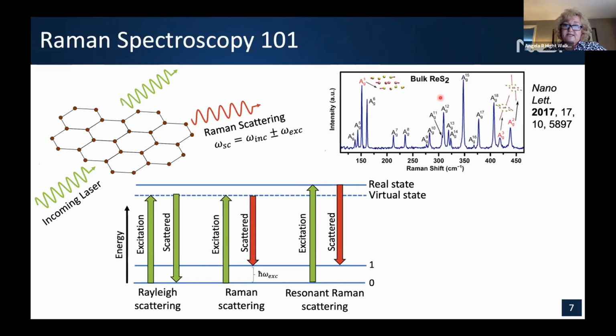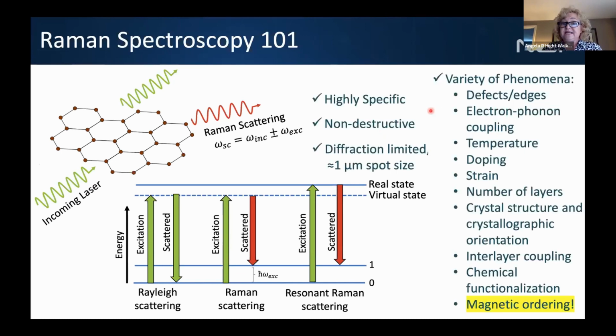So just to give you an example of how a typical Raman spectra might look, we have Raman shift along X and then intensity along Y. This particular example is, again, from one of these 2D materials, rhenium disulfide, which has a plethora of phonons. So it was quite exciting to assign. But the neat thing about Raman, of course, is that it's highly specific, non-destructive if done properly. I always like to put the caveat, it is quite easy to destroy the sample, but it can be done non-destructively. And then, of course, it's diffraction limited.